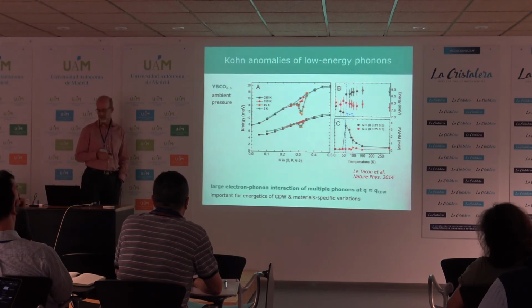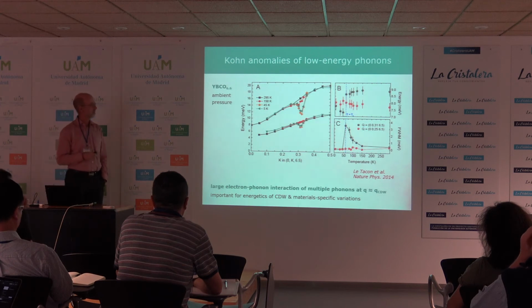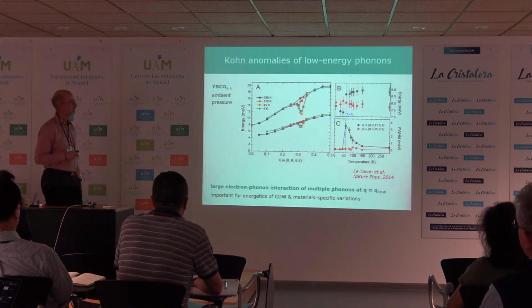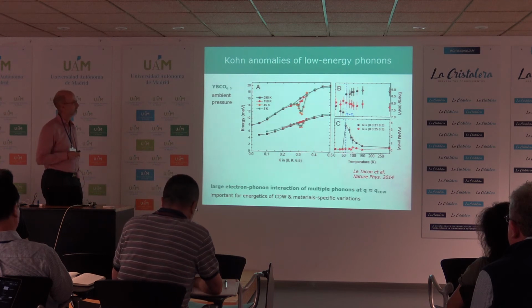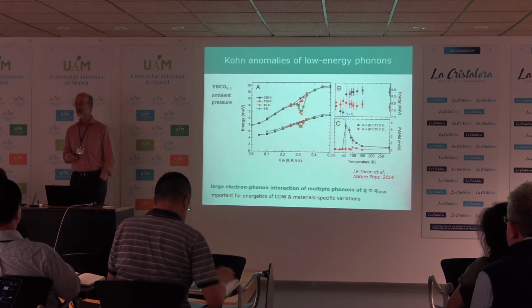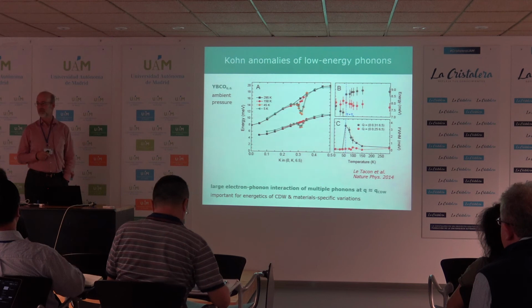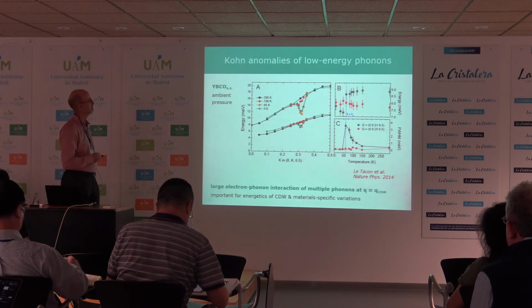So this is something that is not part of the initial work on the charge density wave, but if you now want to get a better understanding of the charge density wave, then you need to also consider electron-phonon interaction. But of course, this electron-phonon coupling favors the charge density wave, which competes against superconductivity. So this should not be mistaken for evidence that the phonons actually enhance superconductivity. It's rather the opposite. That's how I think about this data.